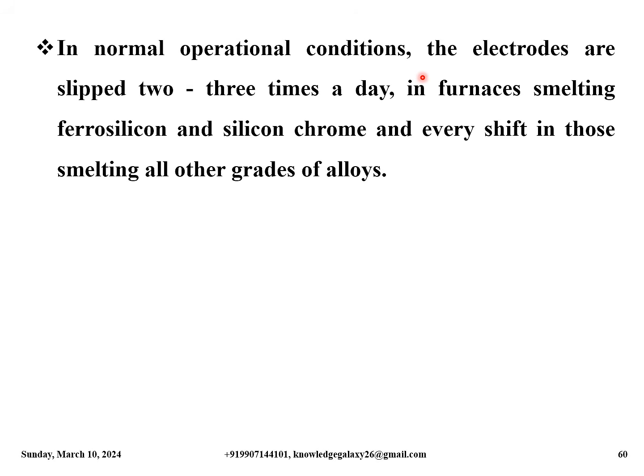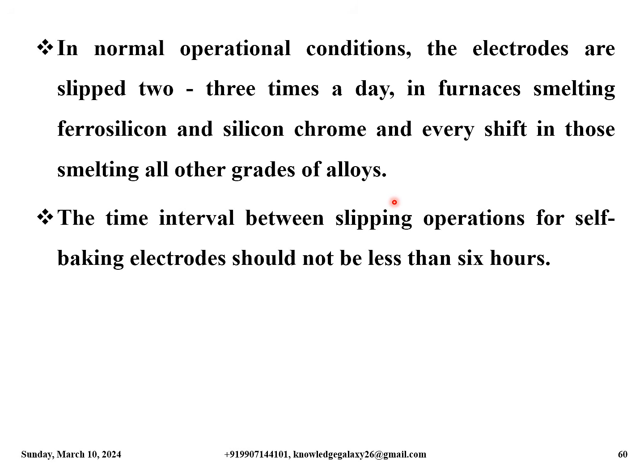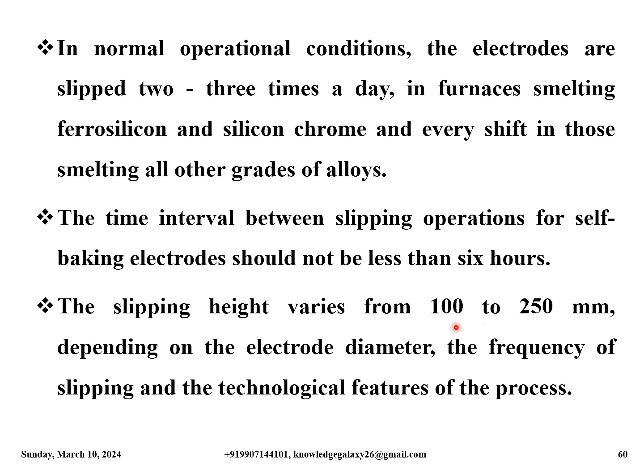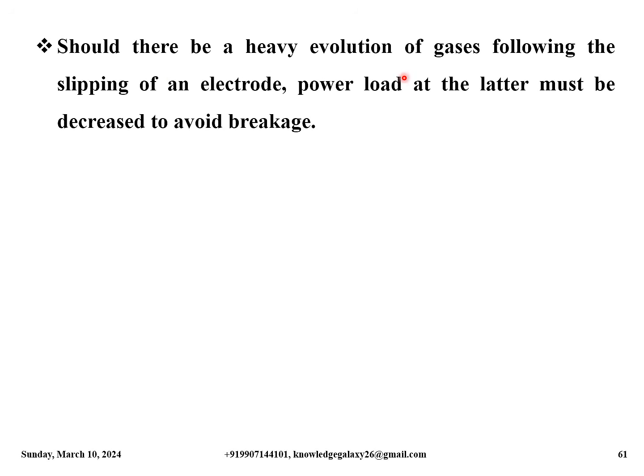In normal operational conditions, the electrodes are slipped 2 or 3 times in a day in furnaces smelting ferrosilicon and silicon chrome, and every shift in those smelting all other grades of the alloys. The time interval between slipping operations for self-baking electrodes should not be less than 6 hours. The slipping height varies from 100 to 250 mm depending on the electrode diameter, the frequency of slipping, and the technological features of the process. Should there be a heavy evolution of gases following the slipping of an electrode, power load at the latter must be decreased to avoid breakage.